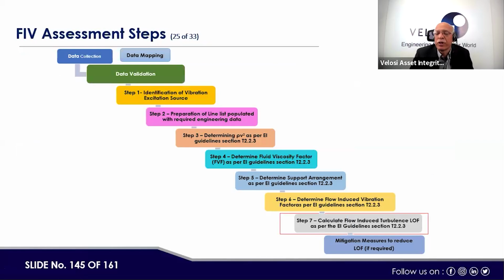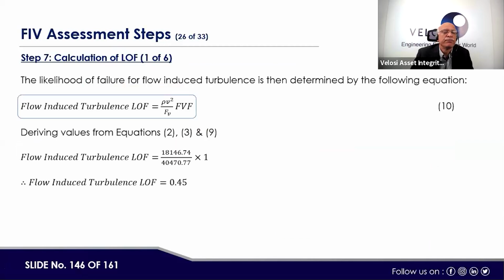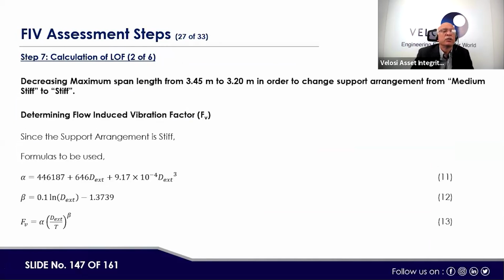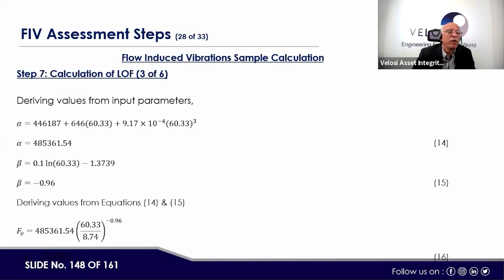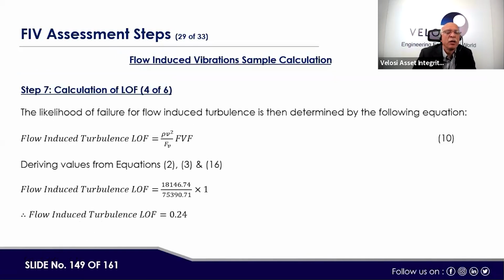Next, calculate flow induced turbulence LOF as per EI guidelines section T2.2.3. This is the formula, and the flow induced turbulence LOF is 0.45 for one of the example lines. Then next is decreasing the maximum span length from 3.45 to 3.2 meters in order to change the support arrangement from medium to stiff, and determine the flow induced vibration accordingly. From a calculation point of view, the alpha beta calculation, the FV number calculation, and then the flow induced turbulence LOF comes to 0.24. By reducing the span of the piping support, the LOF factor is reduced.